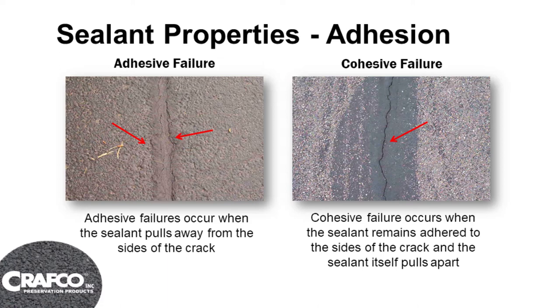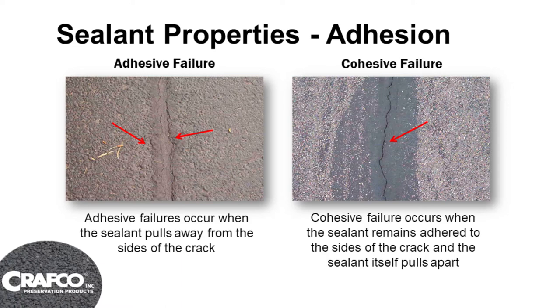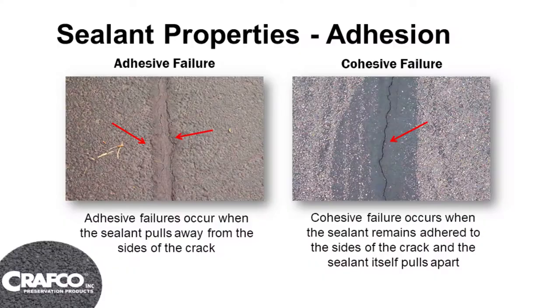The other type of failure is a cohesive failure, where you can see that crack sealant is attached to both sides of the asphalt but cracked right down the center. That's usually caused because the crack sealant is not flexible enough for the amount of movement that surface required. Also keep in mind — for crack sealant to be effective, it needs a crack that's at least an eighth of an inch wide to penetrate into that crack. If you've got narrower than an eighth of an inch, the sealant's not really going to penetrate through. And if they've squeezed all the excess off, leaving just a very thin film over the crack, any movement at all means there's just not going to be enough sealant to adhere or stay bonded.